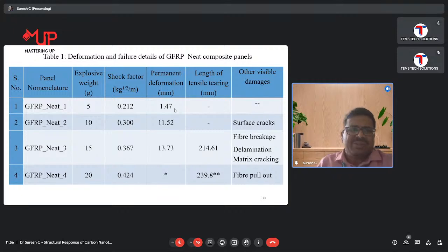When we use 5 gram, the total deformation of the composite panel at the center is 1.47 mm. For 10 gram it is 11.52 mm. For 15 gram it is 13.73 mm. And for 20 gram, there was a complete damage in the structure, so we could not measure the permanent deformation.